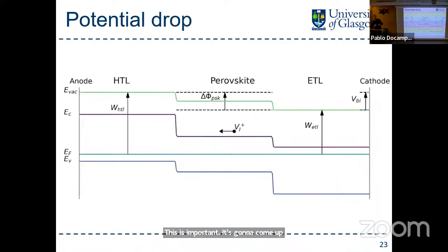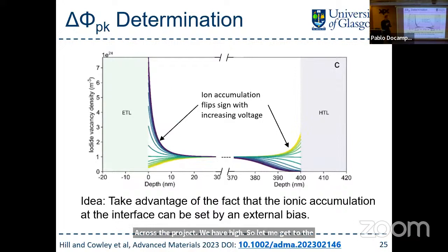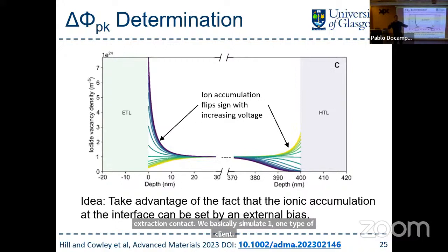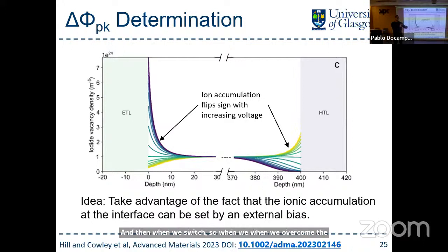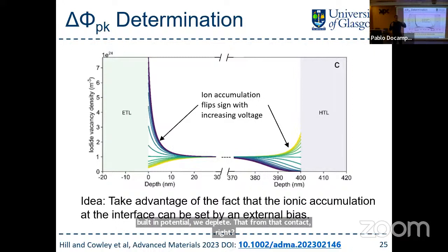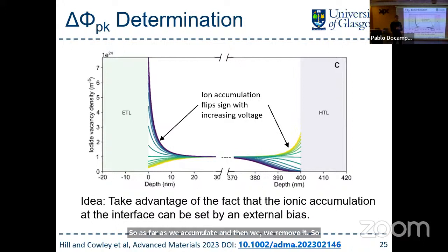So what we characterize with this measurement is the potential drop across the perovskite. As we apply a voltage to the extraction contacts, we accumulate one type of ion, and then when we overcome the built-in potential, we deplete that ion from that contact, right? So at first we accumulate, and then we remove it. Then we flip the sign, because it's always trying to overcome this external bias. The point where the electric field across the device is zero is when it's perfectly screening that built-in potential. So if we can find the moment where the ion accumulation flips, we find out the built-in potential of the solar cell.